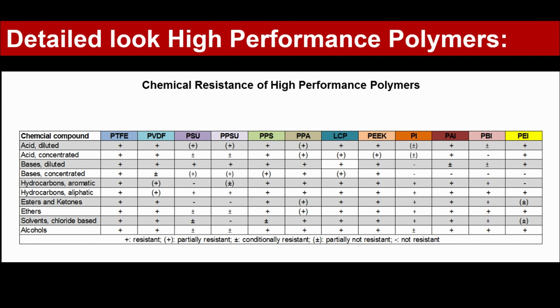In addition to engineering polymers, I also have a table here on the chemical resistance of high-performance polymers. You can clearly see that PTFE, for example, shows no effect from chemicals — the fluorine atoms are much bigger than the backbone, really protecting it from chemical attack. Followed by polyether ether ketone and liquid crystal polymers, which also have excellent chemical resistance. PPS and PPA are also notable — PPS is really resistant up to 200 degrees, and basically no chemical can destroy it. The aromatic structure present in most high-performance polymers is already helping to elevate the chemical resistance level. I will also link this table in the description below.